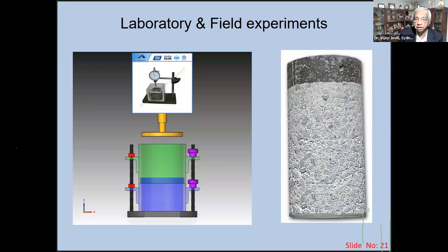And after 1 year, I obtained a core of it, and I tested it in the lab and realized that it gives me 10 MPa strength after 1 year without adding any cement, because the cement part, CaO, is already there in the aggregates. So you don't need a special concrete. Coming back to the highway principle, initially this was a flexible pavement, but over a period of time, it becomes a bound pavement.